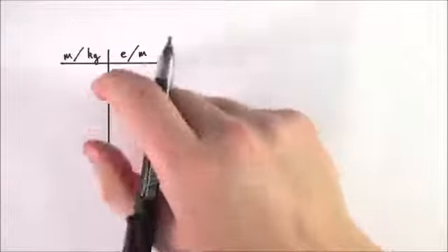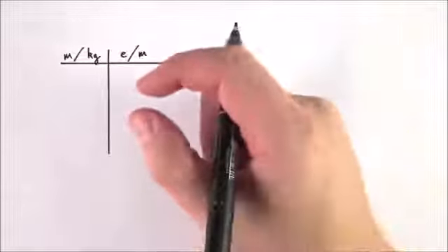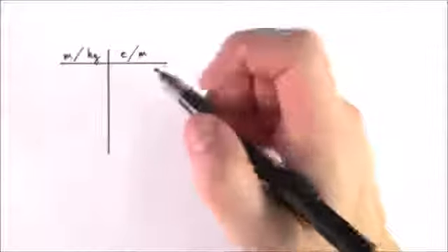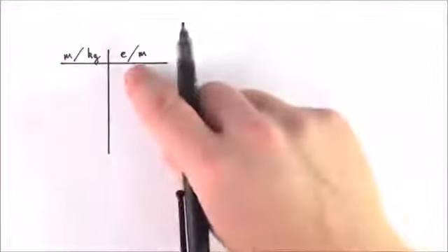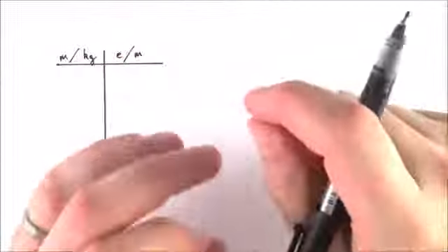Now what you might find is when you put that first mass onto it, and again you've got to have a nice twisted bit at the end of the wire to hold the mass securely, when you first put that maybe 100 grams onto it, you'll find that you get quite a big extension as that wire unkinks. That does not matter, because what you're going to be doing is plotting a graph and looking at the gradient, not the intercept.